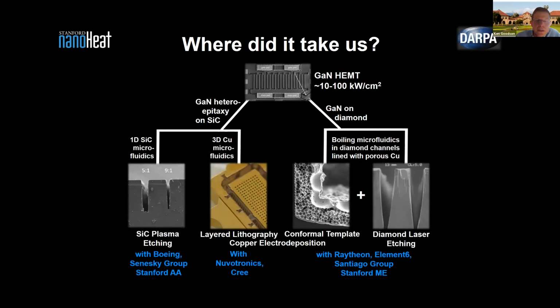In addition, we worked hard on building the heat sinks. So if you bond to silicon carbide, you can either then have silicon carbide plasma etching and build your fluidic channels in the silicon carbide, which is a great heat conductor, or you can actually then attach a copper heat sink, which is a good heat conductor as well, and use these 3D manifolding techniques that I was talking about from my earlier work. And we did that together with Nuvotronics and Cree, and together with Debbie Senesky's group at Stanford, we worked on this.